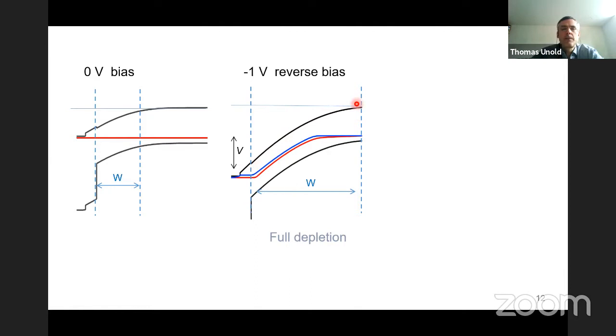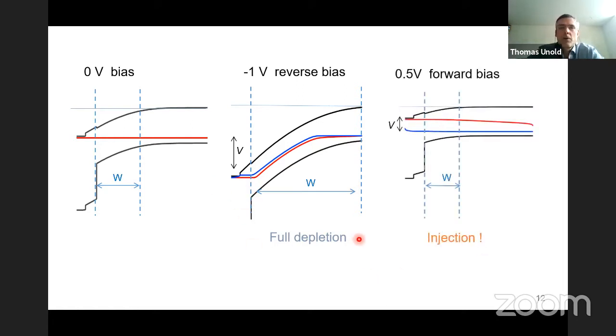So in the case of very low doping, you may even start with this situation. If you increase the bias more, you just deplete it even more, but it doesn't change the capacitance. Capacitance stays really the same, because it's basically always the flat plate capacitor between the two contacts. Now you could say, okay, let's go into forward bias and I can actually decrease my depletion region.